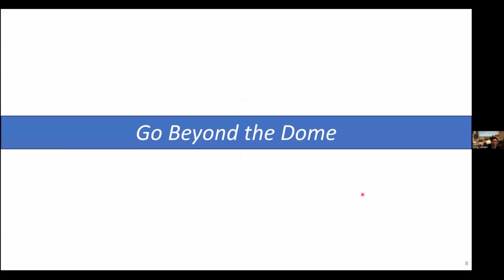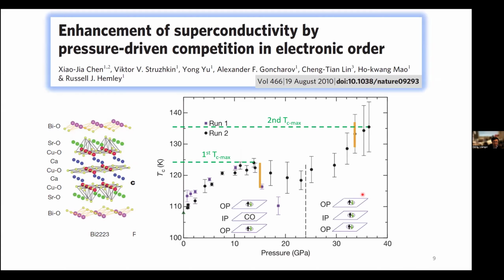So there's a very beautiful work done by Professor Hemley and co-workers back in 2010 on the Bi-based triple layer materials. Firstly, up to around 24 GPa, everything follows the traditional Tc-P relation. That's nothing unexpected, and we reached the first Tc max here around 124, 125 Kelvin. The most exciting thing is after 24 GPa, they continued to push the pressure, and do see another increase of the Tc. So that's phenomenal. That's really nothing we expected to happen.